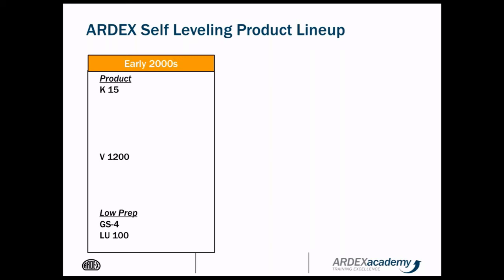comparable to that of concrete, if not higher, but very good flexural strength too. Concrete has a flexural strength of about 400 to 600. The GS4 has a flexural strength of nearly 3 times that, at about 1,500.